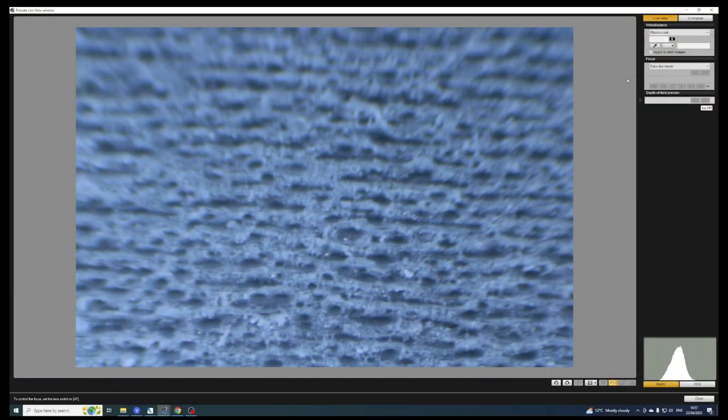Okay so we go and take a look at these under the microscope. What's causing the difference in these two colors? Well first of all let's take a look at the cast acrylic. Here's what my engraving lines look like. Bit weird aren't they? I'm right down to the base material now. And I'm now going to drop the table down so that we move out further and further and further. Now can you see all those bubbles in there? Look at them. Hundreds of them. Everywhere you look there's bubbles.